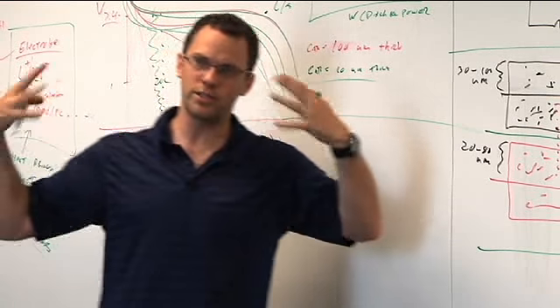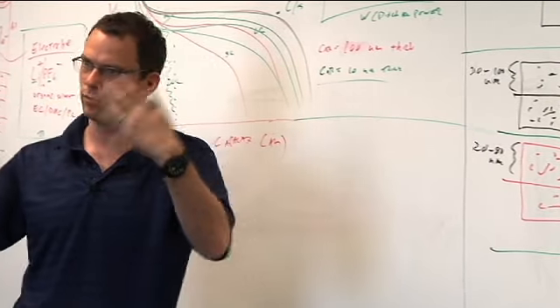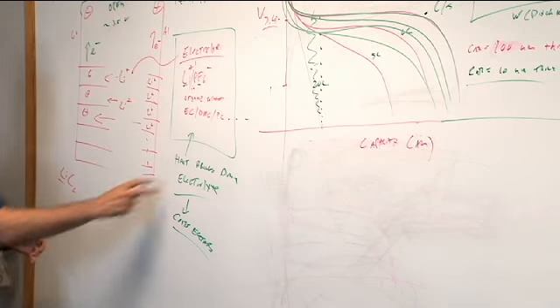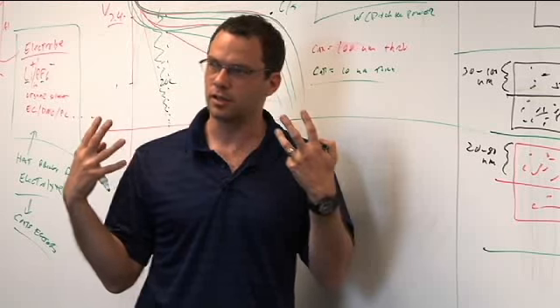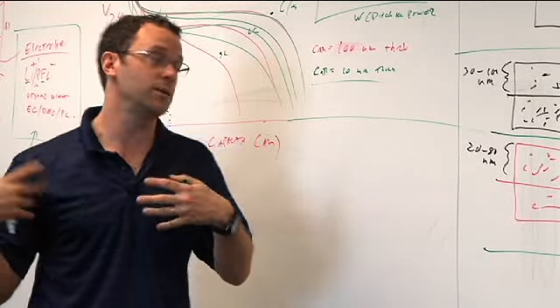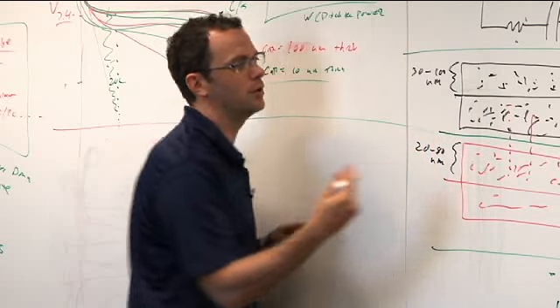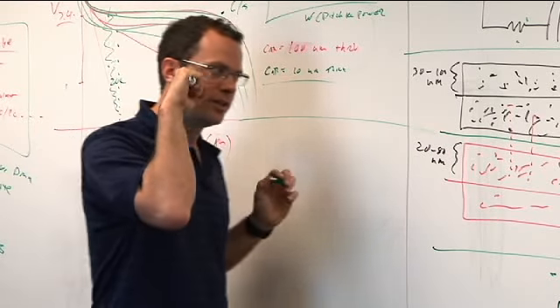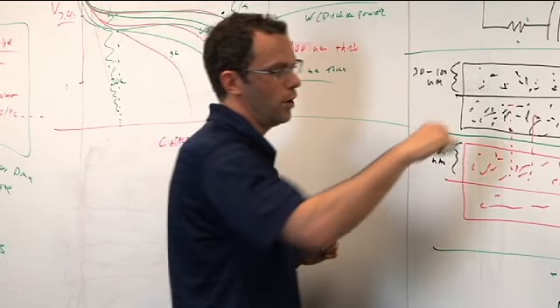You locally heat it up a little bit if you have a short pulse, and that actually increases the diffusion kinetics a little bit. Although long-term heat exposure is bad because of degradation, short-term local heating is good because it greatly enhances the kinetic limitations associated with any chemical system. So you locally heat it up, you enhance local diffusion, but then you either let it sit for a couple seconds or you even do a little bit of a discharge whack as well, just to equilibrate things and shake it around.